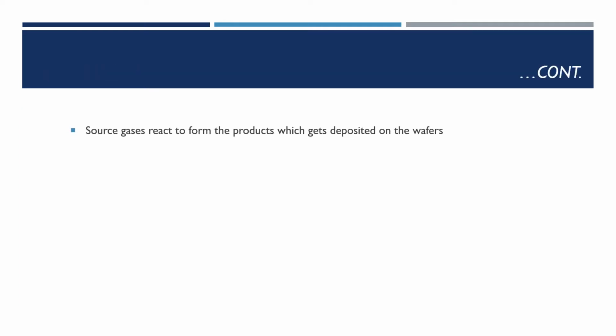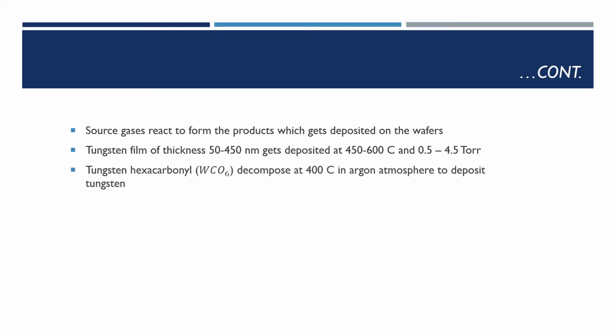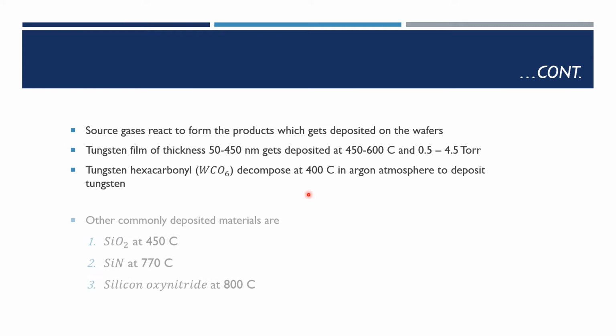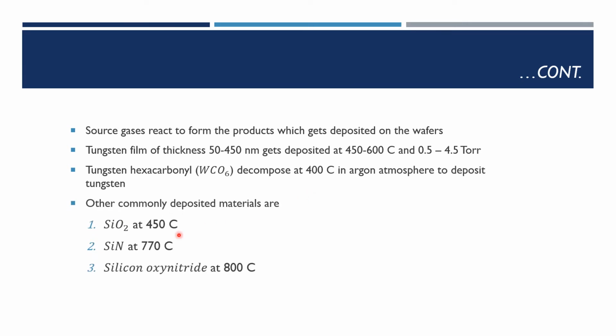Thus the source gases react to form the products which get deposited on the wafers. So we will now see some examples of films deposited on different types of wafers. A tungsten film of thickness 50 to 450 nanometer can be deposited at 450 to 600 degrees Celsius and 0.5 to 4.5 torr pressure. This is done from the decomposition of tungsten hexacarbonyl at 400 degrees Celsius in argon atmosphere. Some other commonly deposited materials are SiO2 at 450 degrees Celsius, silicon nitride at 770 degrees Celsius, and silicon oxynitride, which is a complex compound, at 800 degrees Celsius.